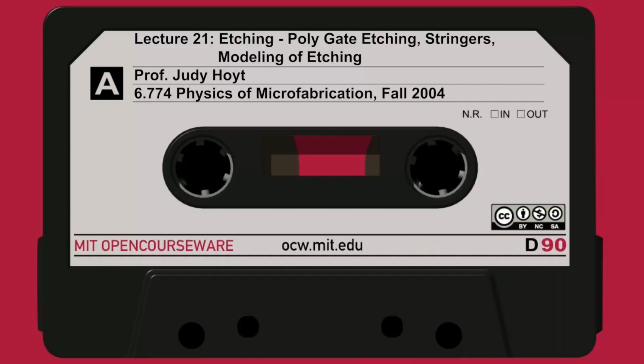There can be impact of different dopants. If the gate is doped prior to etching, which it can be if you put down in situ doped polysilicon, the etch rate for a boron or heavily phosphorus doped poly may be different and it may have different etch characteristics than that of undoped. So you need to take that into account.